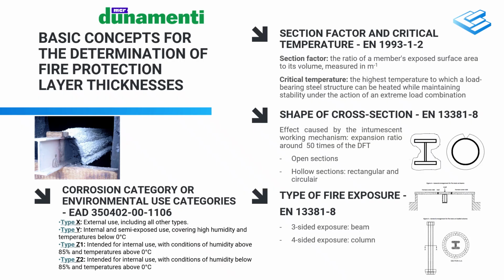Imagine the working mechanism: around 200 degrees Celsius, a carbon-based foam formation begins, resulting in an expansion ratio of 50 times the original dry thickness, and it shows on the picture on the slide. On an open section such as an I-beam, this process occurs without any issue. The foam expands parallel to the flanges and surrounds the section.